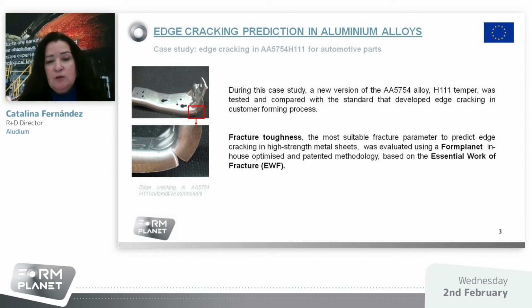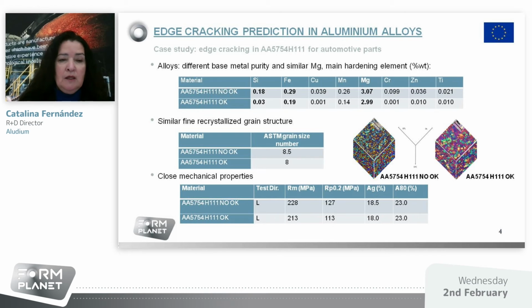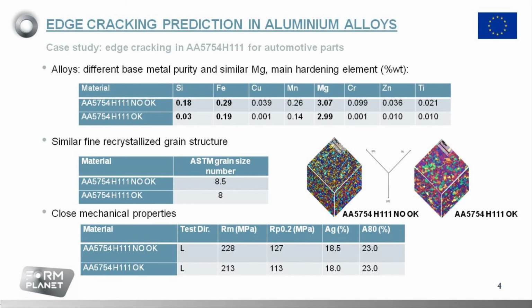Fracture toughness, the most suitable fracture parameter to predict edge cracking in higher strength metal sheets, was evaluated using a FormPlanet in-house methodology based on the essential work of fracture. In Aludium facilities, the chemical composition, microstructure, and standard mechanical properties of both materials, called OK and no OK in this presentation, were determined.